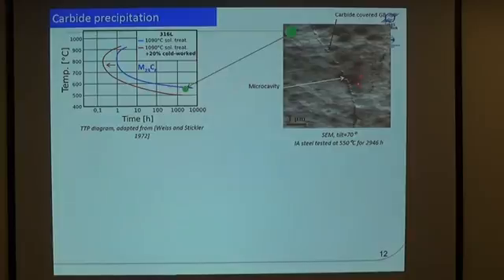So this is just the matrix of all the tests we have performed. And the red ones show damage. Don't care about this. A summary here is on the content and how the materials are resistant to reheat cracking is that this is the least resistant and actually the reason for this is that here we can we have to nucleate carbides and we are for a long time at high stress levels. So if we should give a recommendation to make materials is that the high carbon content is detrimental to reheat cracking resistance and you should put a lot of nitrogen only if the carbon content is low because this one has similar nitrogen but a lot lower carbon and doesn't show reheat cracking.